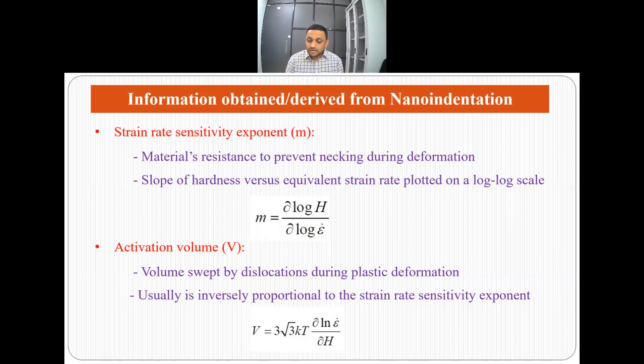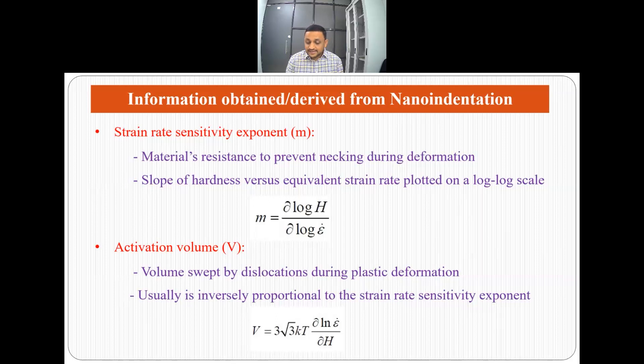The fifth information we can calculate from nano-indentation is activation volume — that is, the volume swept by dislocations during plastic deformation. Activation volume is inversely proportional to the strain rate sensitivity exponent, and can be calculated by V = 3√3 · kT · ∂(ln strain rate) / ∂H. The strain rate sensitivity exponent and the activation volume can help us determine the possible deformation mechanism — the mechanism by which a material is undergoing deformation — and that is why these two parameters play a very important role in the nano-indentation experiment.